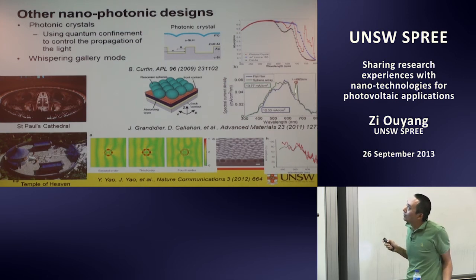But the problem is, again, you only boost at a particular wavelength. And then another bunch of smart guys, they think, oh, we can lower the quality factor, so we can introduce second order, third order, fourth order modes, and let them be bound inside. And instead of using an anti-reflection coating on top, why don't we just make the absorber layer like this? So this is actually a PIN structure. They make nanocrystal silicon thin film material like this. This is the active layer. So the sphere itself is the absorber layer. So they can have multiple coupling of the light at different frequencies, and they claim they have very high absorption.